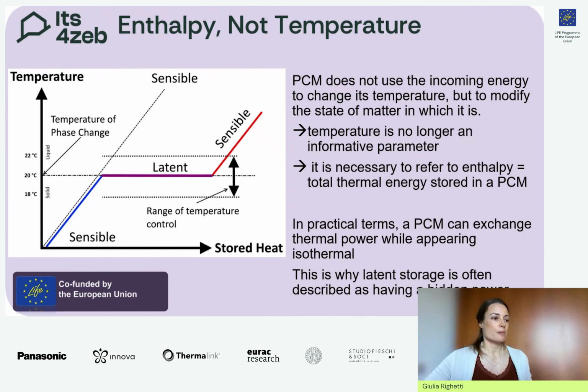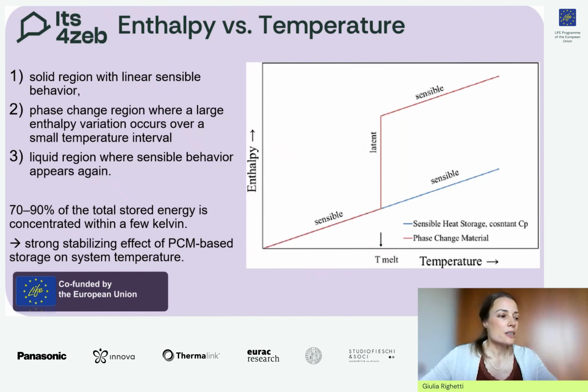So in practical terms, a PCM system, a latent system, can exchange a lot of energy, a lot of kilowatts of thermal power, while appearing almost isothermal. This is the reason why latent storages are described as having a hidden power, because the energy flow is not visible if we look at the temperature. So for this reason, when we refer to latent storages, we have to refer to enthalpy, which represents the total thermal energy stored in the material, including the sensible and the latent contributions.